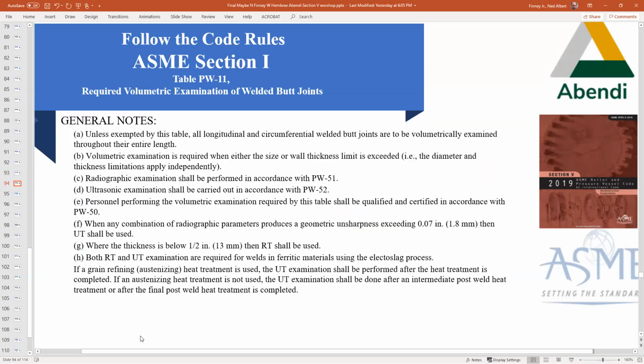General notes. This one's real important, and this is under the table. I'm not going to go through all of them, but I'll turn your attention to Charlie and Delta, radiography and ultrasonics. It gives the specific acceptance criteria. So again, for the volumetric NDE that's being performed, where is it located? It's located in that construction code. PW 51 for radiography and PW 52 for ultrasonics. The next one is very important. Every one of them are important, by the way, but I just highlighted a couple of them here. Echo, personnel performing the volumetric examination required by this table shall be qualified and certified in accordance with PW 50 that we previously discussed. It says, when any combination of radiographic parameters produce a geometric unsharpness exceeding 0.07, then UT shall be used.